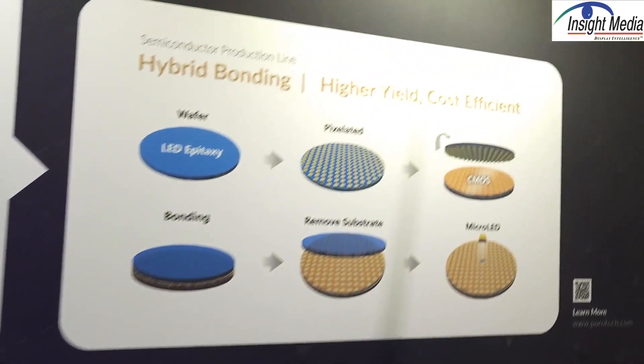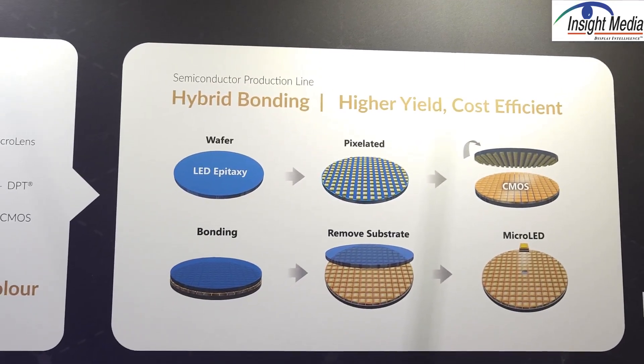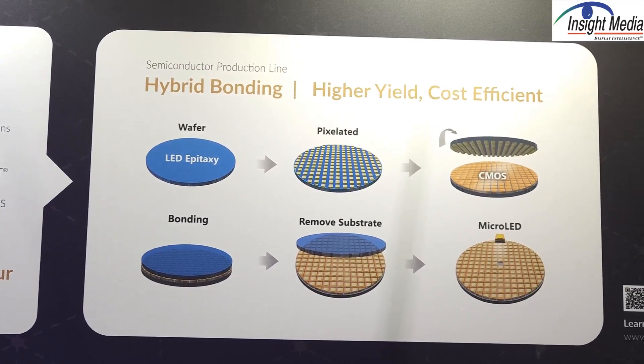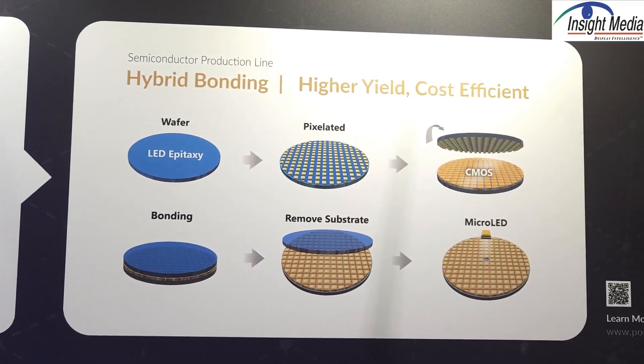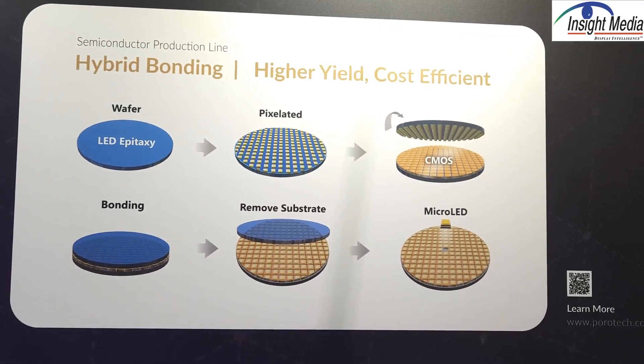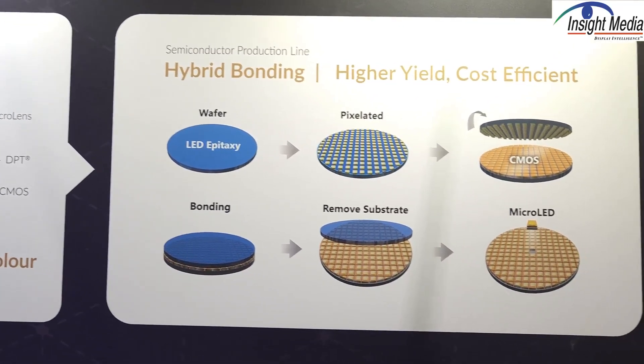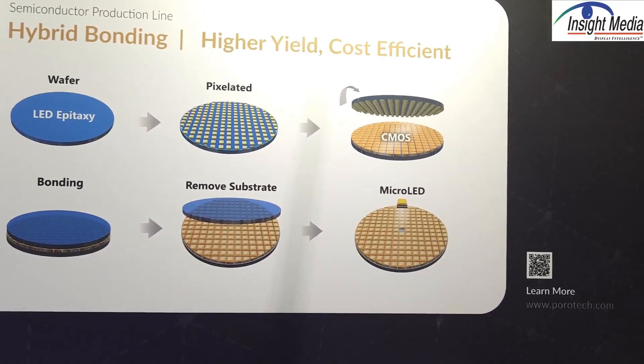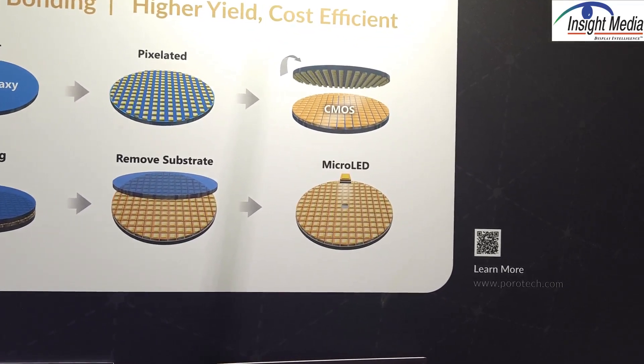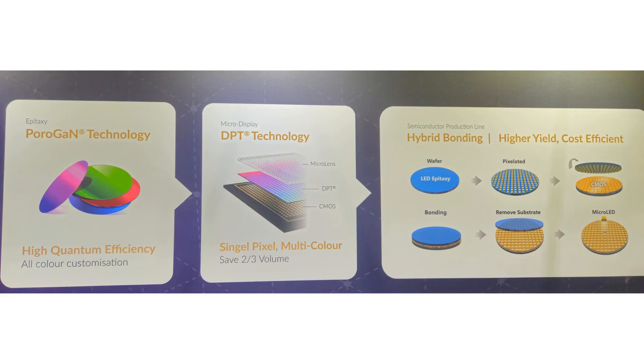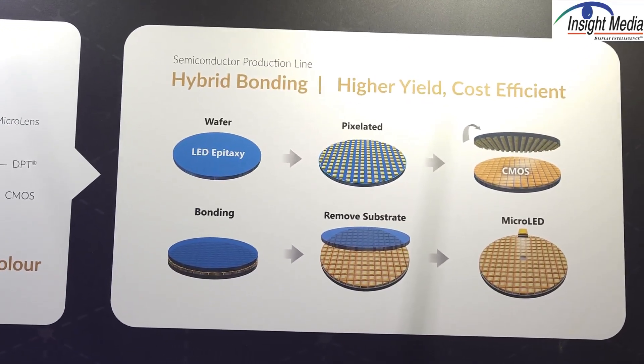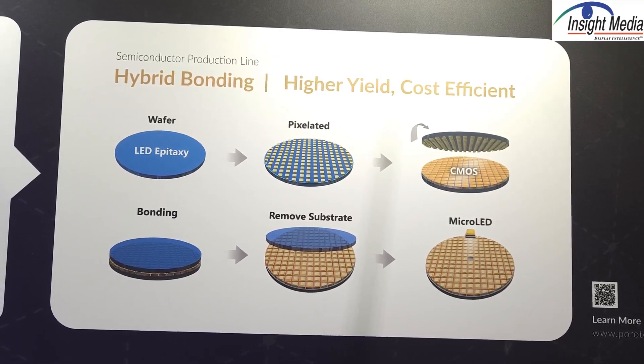This is their full workflow. They process the LED epi wafers themselves because they have this special poro layer to create the DPT pixel. It's pixelated, and because this is all done on silicon, they then mate that in a wafer bonding process to the CMOS driving circuit, and pixelate and separate those. This is one of the key ecosystems that's starting to develop — Porotech and the Foxconn group trying to develop a more mass-produced ecosystem for micro-LEDs.